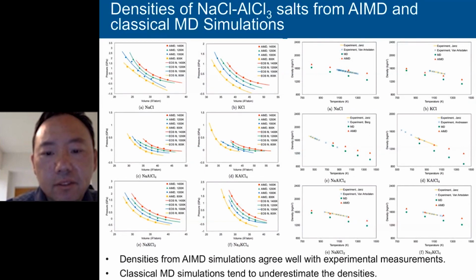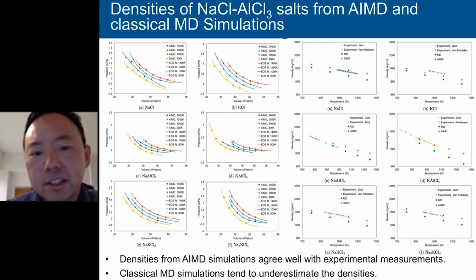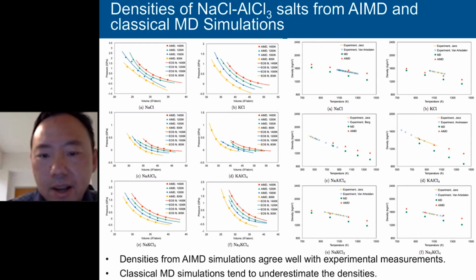Here the left figure shows the calculation of the densities of these salts using Ab Initio MD. Essentially what I did is I calculated the pressures at 5 different volumes for each liquid and fitted them to an equation of state. Extrapolating to zero pressure will give you the equilibrium volume. If you look closely, you can see that these curves are very flat, especially close to zero. That means the potential has to be very accurate in order to capture this very slow decay tail. Unfortunately, this tail gives you the equilibrium volume.